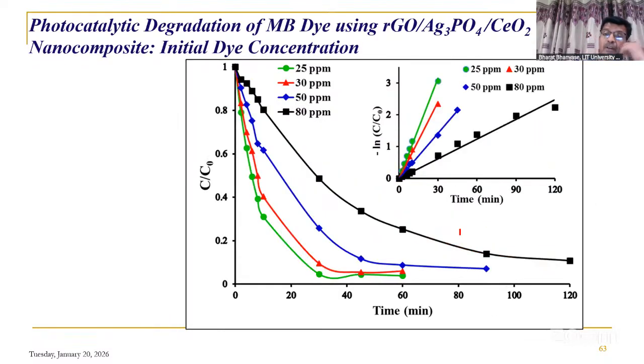Here, initial concentration of dye was studied. When there is less concentration, catalyst being fixed, the reaction rate will be more because pollutant molecules are less in number. But if concentration increases, the pollutant molecule, that is MB-dye molecule, will increase while catalyst remains fixed in amount, so the degradation rate will decrease. But anyhow, it is more than 80%.